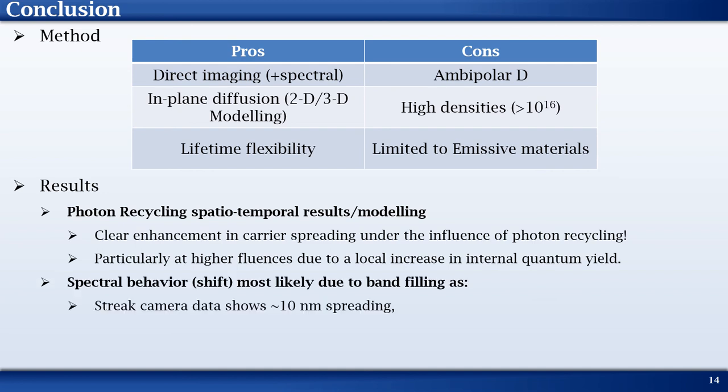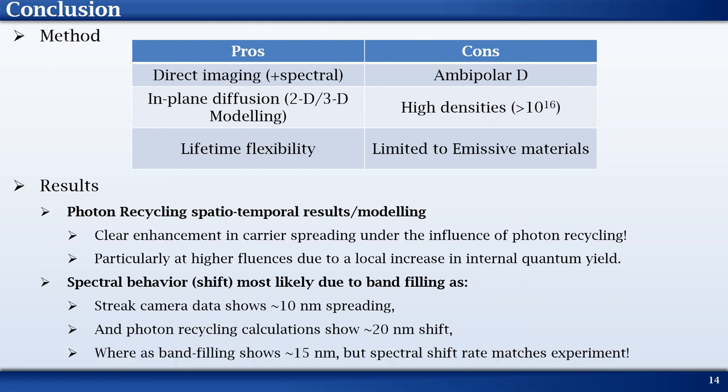As for the observed redshift in our spectral measurements, we explored both photon recycling as well as bandfilling as potential causes. Among the two, bandfilling results explain the spectral shift much better. Although we did not completely explain the varying spreading regimes, these calculations bring further clarity to the nature of spreading when photon recycling is present.